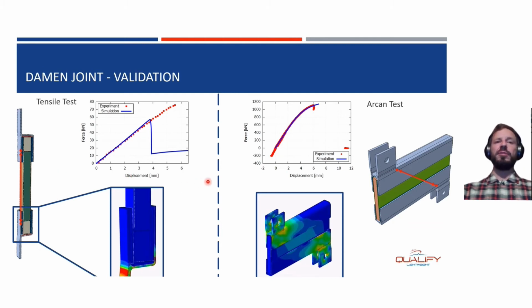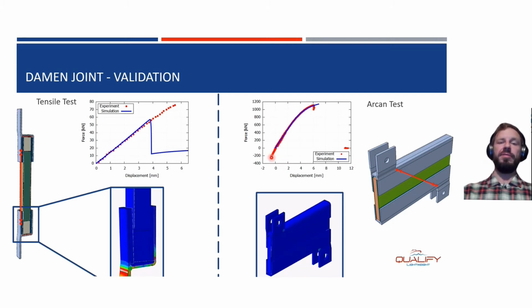It's a good agreement. And the same good agreement has also been achieved with the Arcan test you see on the right-hand side. We then did a virtual extensometer test, relative displacements between those two points, to get the force displacement curve. Damage was not included in those modeling approaches for the simple reason that it was high complexity. We observed some yielding of the flange here. We observed yielding of the adhesive way before the whole joint failed. So at the moment, we still didn't look into the failure. That's still under investigation. Yet, we have achieved relatively good agreement here.